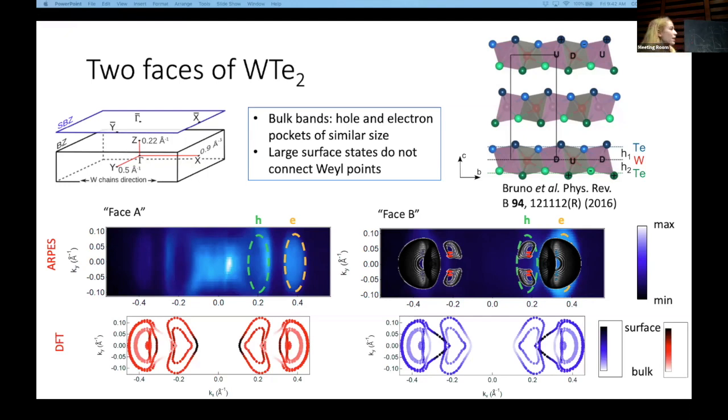You probably see these states near gamma, and these also show up in the calculations, but it turns out that they're just a little bit below EF, which is why they don't show up in these contours, which are exactly at EF. With photoemission Fermi surface maps, we have some integration window in energy, which makes us see states that are just a little bit below EF.